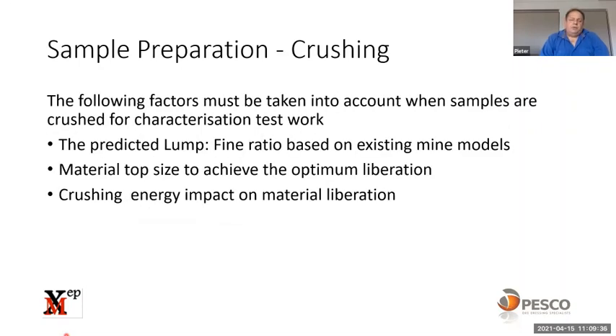So as I explained before, when you do crushing, you need to know exactly what top size you are aiming at, and also let your crushed sample represent what's happening in the plant. I know there's different types of crushers in the labs, and there's different types of crushers in the plants. So when you use your lab crusher, make sure you generate the same energy in crushing, generate the same type of liberation when you do crushing compared to in the production unit. So if you've got a jaw crusher and a cone crusher in the plant, use the same type of jaw crusher and cone crusher in the lab. Don't use disc crushers or high pressure grinding rolls or something else, because that will definitely influence the liberation of your material.